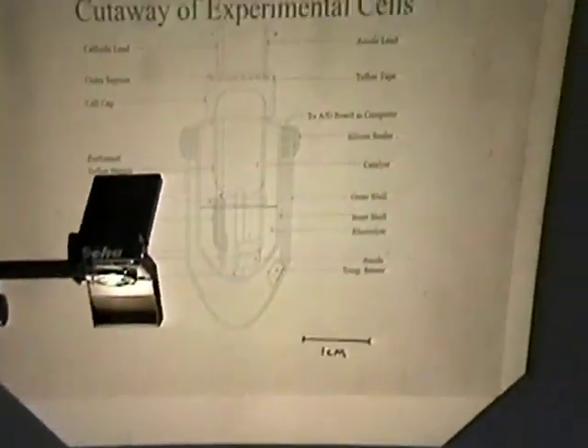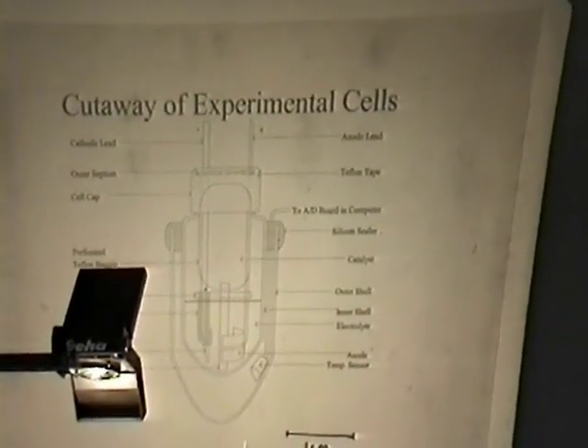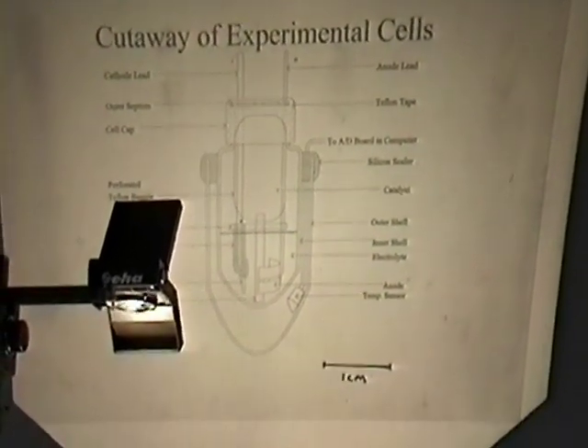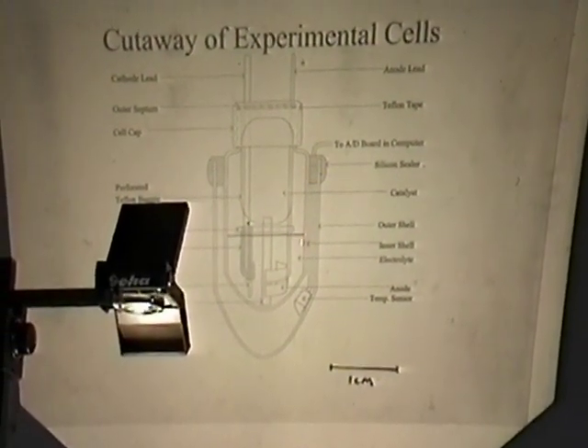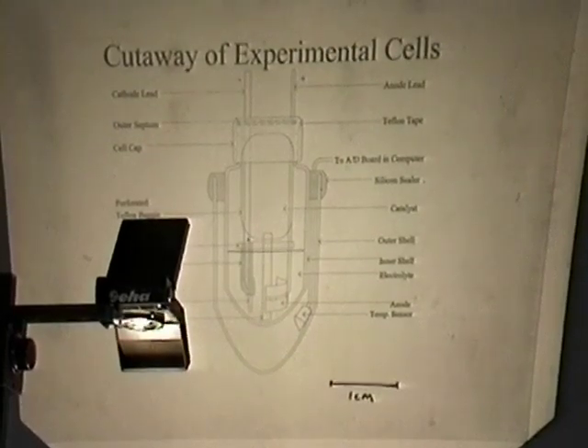A typical cell for this 8-cell experiment is shown up here. And you can see that this is a pretty small cell by the scale here. We have an outer glass shell with an inner glass shell. This is dead airspace in here where we put a temperature sensor. Inside the inner tube here, we have just enough room for 3.5 grams of electrolyte, which is heavy water and sulfuric acid. And we have just enough room for about 3.5 grams of catalyst. Here we have a platinum lead, which is attached to a titanium cathode. And we have a platinum anode, which is also attached to a platinum lead.